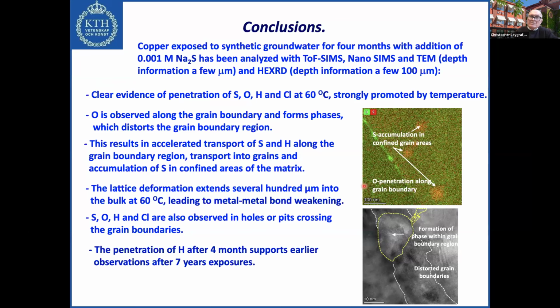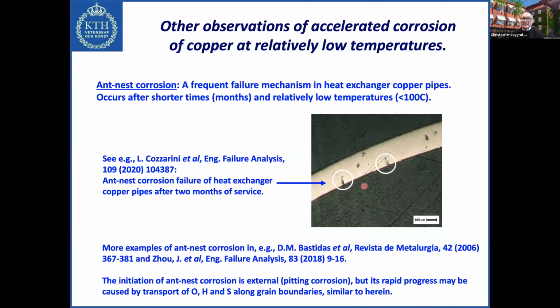But in fact, there have been other observations of accelerated corrosion of copper at relatively low temperatures. There is a phenomenon called ant nest corrosion, which is a frequent failure mechanism in heat exchanger copper pipes. It also occurs after shorter times, months typically, and relatively low temperatures, typically below 100 degrees Celsius. Here's just one example of a result showing the cross-section of a copper wall. And you can see that this is ant nest corrosion of a heat exchanger copper pipe after 2 months of service. And there are several other examples when we look into the literature.